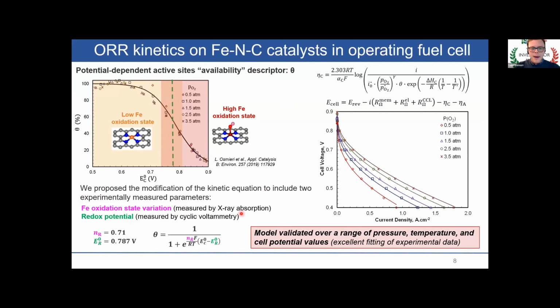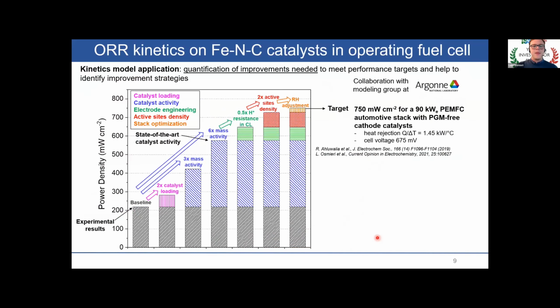By inserting these terms in the overall kinetic equation, we were able to fit with a very good agreement a broad range of experimental data collected at various operating conditions in terms of temperature, pressure, and in a broad range of potentials. So we have validated our model, which was later applied in another work in order to quantify the improvements that are needed to meet the performance target goals, and also identify what are the possible improvement strategies.